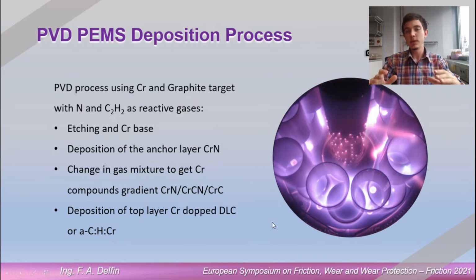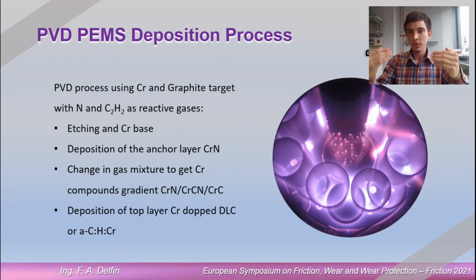So particularly in this case, for this DLC, we got an anchor layer of chromium nitride before the DLC coating. So we put our chromium target with nitrogen reactive gas, so we form this chromium nitride. Then we start putting acetylene inside the chamber, so we get a gradient of chromium compounds deposit over the chromium nitride. So we go from chromium nitride, chromium carbonitride, and then chromium carbide on top.